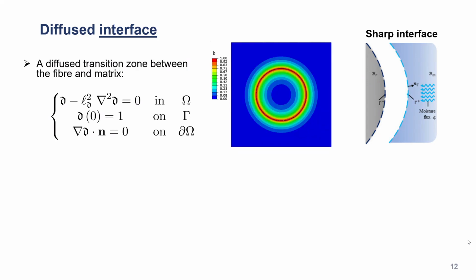One last puzzle we want to fill is the interface. How are we going to model the fiber matrix interface here? Basically, the cohesive zone model assumes a sharp interface. In that sense, we want to model these fractures at the interface and also model the moisture across the interface. To do that, we use the phase field method again here. We approximate this interface by diffuse regions so that we can easily couple the moisture transport problem here.